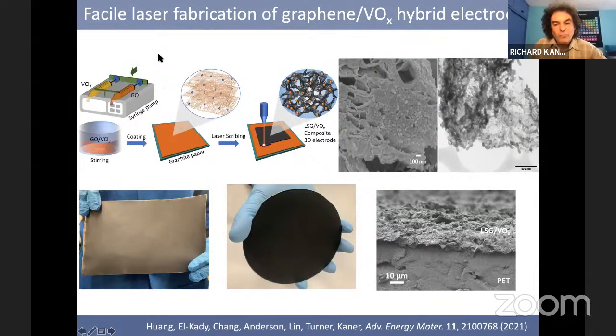Now, some of our very recent work is to put in things like vanadium dioxide, because you can actually store more energy using this. And so what we've been using here is a combination of vanadium chloride and graphite oxide. And so we can just coat this on graphite paper. We can hit it with a laser. And so we can make this complex that is really a composite between vanadium oxide and graphene after hitting it with a laser. And you can scale this quite massively. You can see this very large piece, and here you can make some round structures, and you can see what it looks like under a microscope. And if you're more interested, a paper on this just came out this past month in Advanced Energy Materials describing this in much more detail.